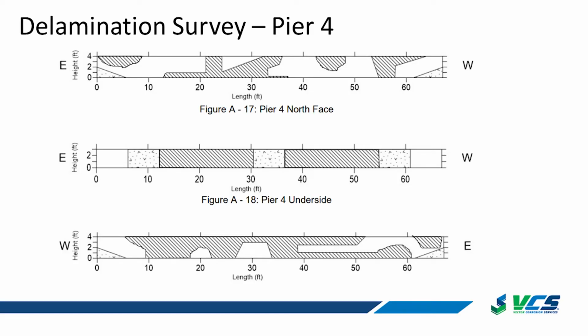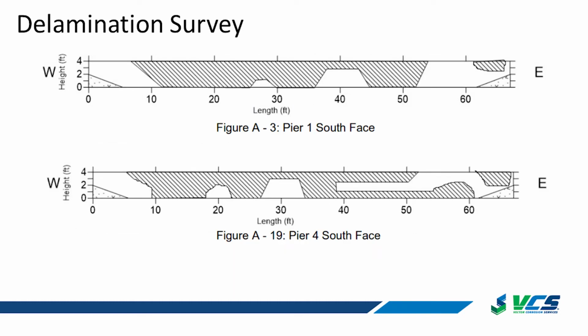And then if we go to Pier 4, which had the CP, you can see there's pretty significant delamination, effectively the same amount of surface area, unfortunately. So if I take just the south face for Pier 1 and Pier 4, effectively there's really no difference between the two. So that's an unfortunate sign that it really didn't provide much benefit. We still have a lot of concrete repair work there.